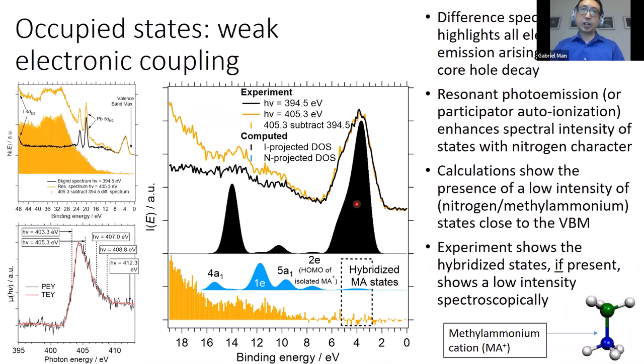So now we're going to look at the occupied states. On the left-hand side here, I'm showing two decay spectra associated with two excitation energies. The black spectrum was recorded at 394.5, so that's around here in the absorption spectrum. And the orange one was recorded at 405.3, so it's close to the main edge over here. Once we're on resonance, we see a lot of nitrogen-related decay.